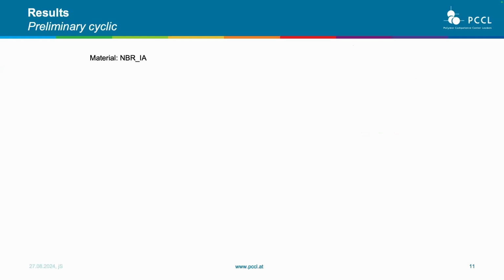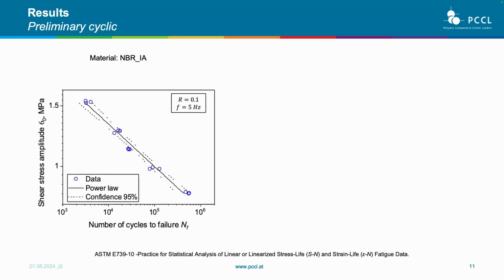Just keep in mind this, and then we move to the cyclic test. So the cyclic test, we did some sort of Wöhler curve. We apply different loading levels, and then we observe what was going on. And what we got was a really good Wöhler curve line, with really good reproducibility in general. And it was actually surprising, because if you ever work with rubbers, it's really complex and they normally have big scattering. So this is really a good result statistically for us.